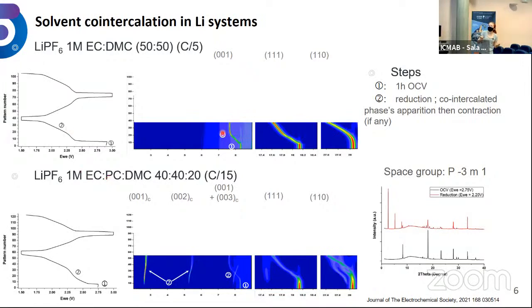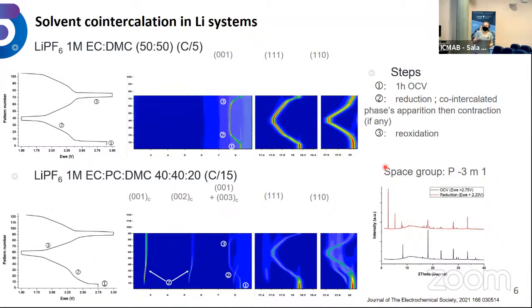you can see that the peaks are shifting toward lower angles as more lithium is intercalated between the layers of titanium disulfide. However, when the cell contains propylene carbonate, you see the 3 characteristic peaks of the co-intercalation, and I represented both patterns at the end of the reduction, and you can see they are much more intense than the lithium intercalated phase. When you start oxidizing your cell, the peaks of the lithium intercalated phase shift back to their original position, but the co-intercalation remains unchanged. So this is irreversible.